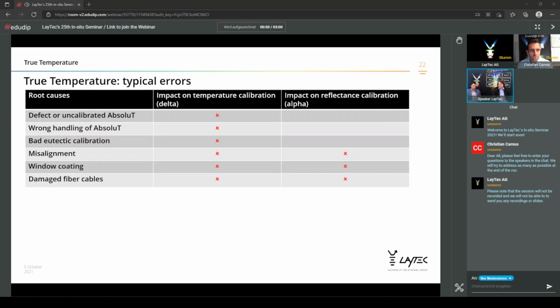I mentioned damaged fiber cables. That does not mean that the fiber cables are as fragile as a raw egg or thin glass; they are quite robust. But on the other hand, you have to treat them pretty well in order not to damage the inner fiber core. Keep in mind that the inner core has a diameter of 600 micrometer and only allows a minimum bending radius. Any radius smaller than the minimum allowed bending radius bears a very high risk of damaging or cracking this inner fiber core.